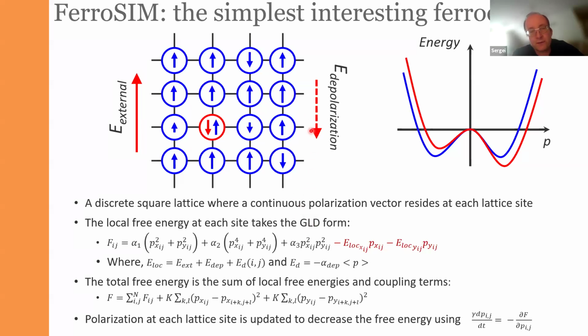The reason why we adopted this model, which was proposed by a gentleman whose name I forgot around 2000, is because this model is ideally matched to the nature of observations in the electron microscope. In the electron microscope, we see the individual atomic columns. So the in-plane polarization is defined on discrete positions, but along the z direction, it's averaged along the beam path. So we felt that it is the right way to match the complexity of physics and the observational model. So that's all you need to know about it.